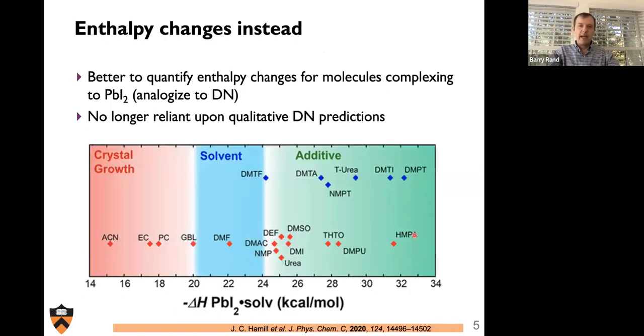It was found later by Clay and others like Jeff Schwartz and Lin Liu and Paulette Clancy that one could more accurately quantify not using the donor number, but something analogous to it, which is basically the enthalpy change for molecules complexing to lead iodide. So you look at the change in enthalpy of lead iodide as a different ligand interacts with it. And this was more quantitative compared to the donor number.